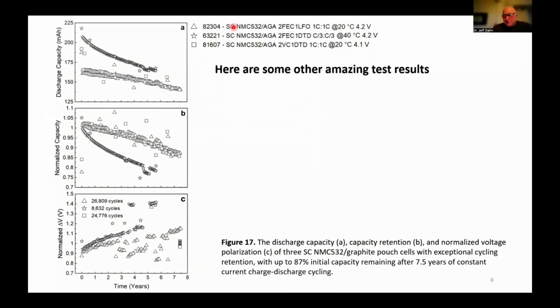And the single crystal materials show incredible lifetime. A lot of manufacturers around the world are switching to single crystal materials of all different types of NMC. So here we have 50% nickel in NMC 532, but single crystal with 83% nickel, 92% nickel. All these materials are becoming much more popular these days because of the really long lifetime that they give.